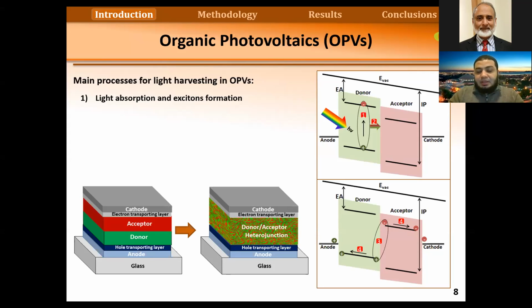For organic materials, organic semiconductors in general, they have a high binding energy, which means when they absorb light, they form what is called an exciton. The exciton, as you see here, is an electron and hole, but they are bound. They have a very strong binding energy between the electron and hole, and they are bound together. So this makes it difficult to separate them. To separate them, they need to diffuse to an interface of p-type material and n-type material, and then at the interface they can phase separate. The electron will go to the n-type material, and the hole will go to the p-type material.